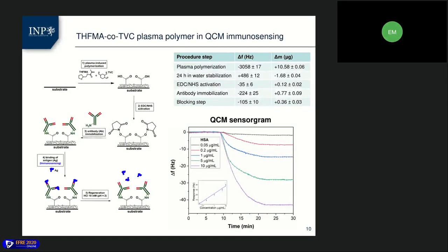After our thorough study of stability of the obtained films, we tested them as matrix layers for immobilization of antibody molecules in QCM immunosensing. The biosensor preparation procedure included several steps. So first, the QCM crystal was coated with the plasma polymer film. Then the film was immersed for 24 hours in water for stabilization. Then activation of carboxyl groups present in the film was carried out by reaction with EDC-NHS, which is carbodiimide succinimide chemistry. And then right after the activation procedure, antibody was covalently bound to the surface of the sensor.